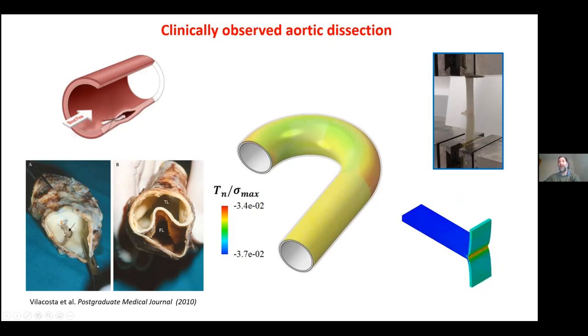So this test is completely inappropriate, because here we're putting tension between the two layers, and in the physiological loading, we have compression between the two layers. So that tells me that the crack should never grow in this manner in the body. So this kind of test that you see everywhere in the literature isn't so helpful.